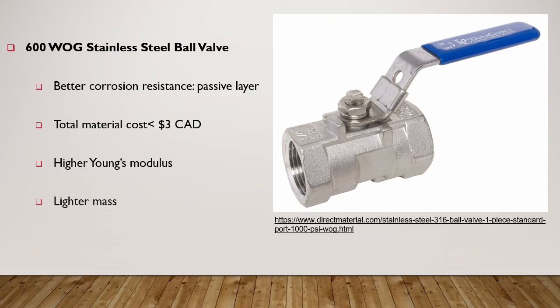Since the price of stainless steel is only around 1.5 to 1.6 Canadian dollars per kilogram, and we also specify the maximum weight is 0.5 kilogram, this means the total material cost will be around 0.75 to 0.8 Canadian dollars per valve. This is pretty cheap. Also, the Young's modulus for stainless steel is much higher than brass. This will provide extra strength on handling hoop stress. Plus, the low density of stainless steel will reduce the applied load to the whole piping system and save the transportation cost.